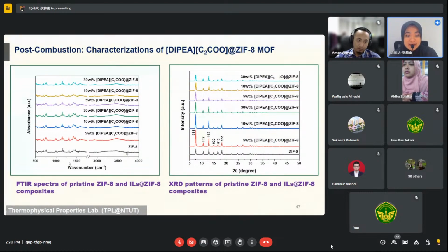Basically they are not that much different from the ZIF-8. It's almost the same, like the stretching bond, for example around 3,465. All of these have a peak. So it's just to confirm that when you combine or composite, we call it a composite, with the ZIF-8 itself, there is no change. If there is a change, it means maybe it's not the chemical we want, but it changed to another form. The same for the XRD pattern, from 011 up to 222 it is almost the same here. So nothing is that much different from the pristine ZIF-8.